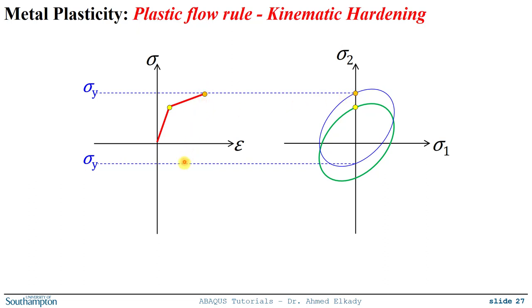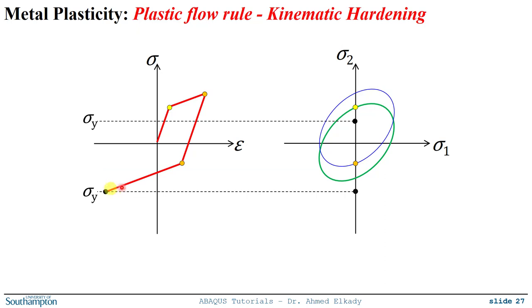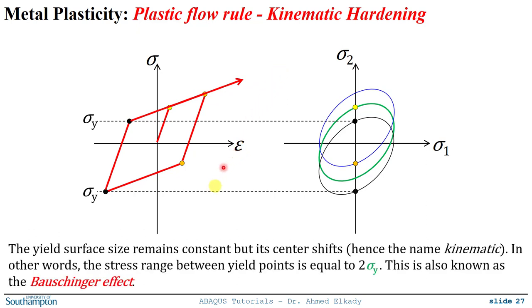So now if I unload from this point, my yield point will be the intersection of the unloading slope with this range over here. So if I stop at this point, and then if I keep increasing and I stop, let's say, at this point, so this means if I stop here, then my new yield surface is shifted again, and so on. If I go back, this will be my new yield point, and so on. So what you notice here is that the yield surface size remains constant, but its center shifts. That's why we call it kinematic, because it keeps moving. The yield surface keeps moving.